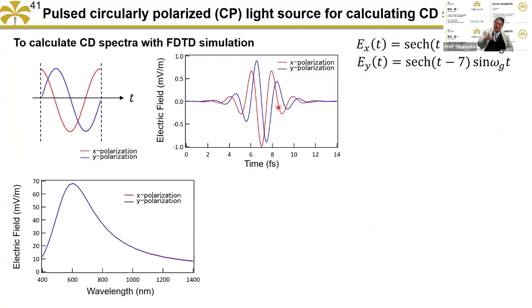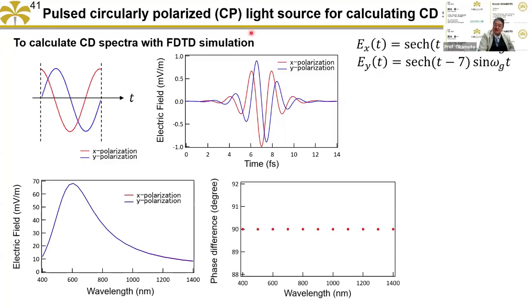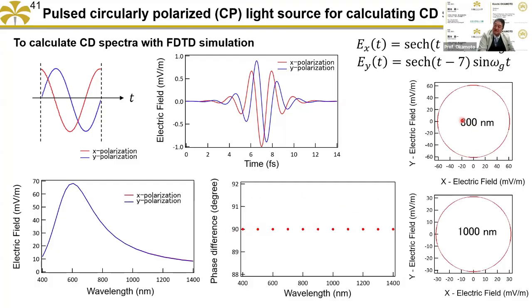Usually for CD simulation, people use CW light for each wavelength. But if so, it takes a very long time. We want to use one pulse to get the spectra at the same time, but the usual pulse is not good enough. So we thought about many types of functions, and finally we found this function. This function is very good for pulsed circularly polarized light. In this function, the phase shift is almost 90 degrees over a wide wavelength region, and for each wavelength a very beautiful circular polarization is achieved.